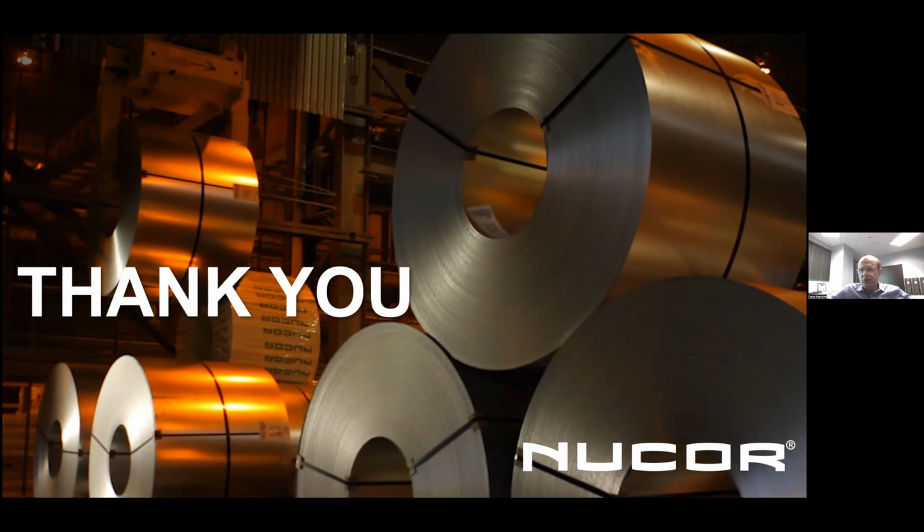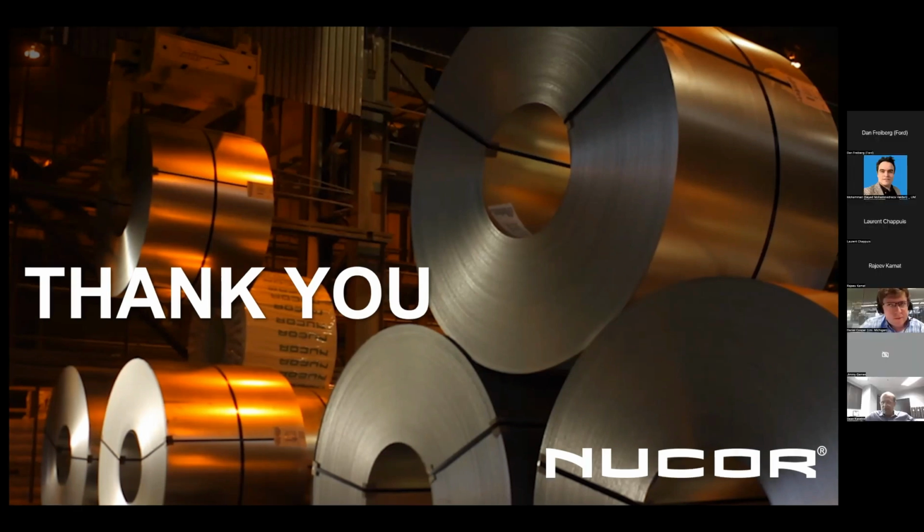And I can tell you that in 2022, because of the relative shortage of pig iron due to the Ukrainian conflict, we cut our pig iron consumption in half. So pig iron isn't necessary, but it does improve our processing as far as cycle times to produce steel. So we tend to use some pig iron. So it becomes part of that equation as well.